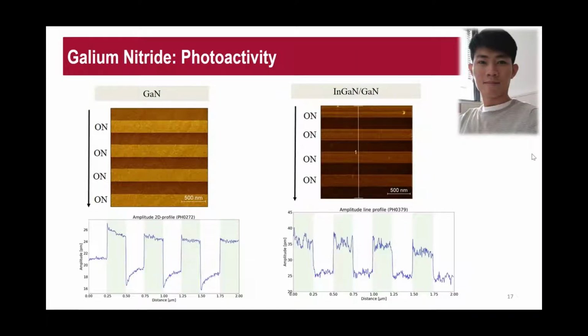And the next is we make use of PFM to study gallium nitride. For this, we would like to understand the photoactivity behavior in gallium nitride. We understand that GaN is a very common material in LED and micro LED as well. So we try to compare GaN materials with InGaN materials, and we are looking at the strain behavior as a response to light. We understand that GaN is not a ferroelectric, but it is a very good piezoelectric material because it has a very high d33 coefficient.